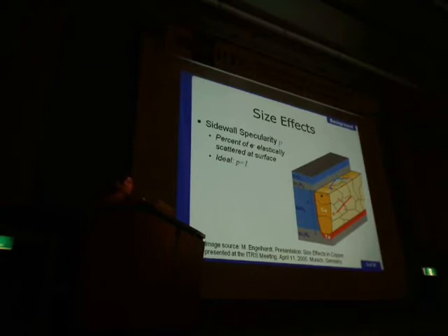So what that means in plain English is when an electron approaches the surface, it decides whether or not it's going to preserve its drift velocity and continue onward, or if it's just going to stop at the edge. And so what we have here is, ideally, as a parameter, if all electrons encountering the sidewall were to have a scattering parameter of 1, they would lose no energy and continue down the conductor.